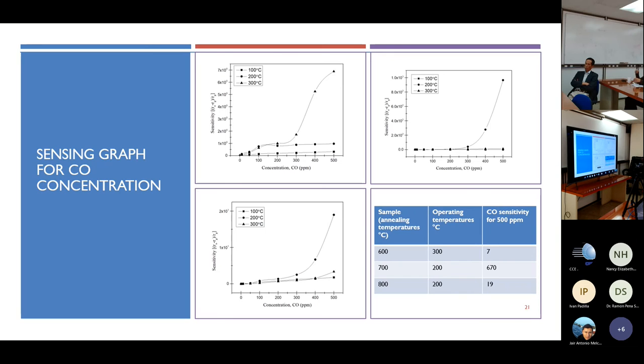For CO, it plots the sensitivity against the concentration in ppm at the three operating temperatures. In this graph for 600, 700, and 800, at 100 and 200 degrees Celsius operating temperature the peak is very low, while at 300 degrees Celsius the electrons get excited at high temperature and the electron flow is greater. At the low concentrations of 100, 200, and 300 ppm there is no good sensitivity. At 500 ppm, it shows a good sensitivity.